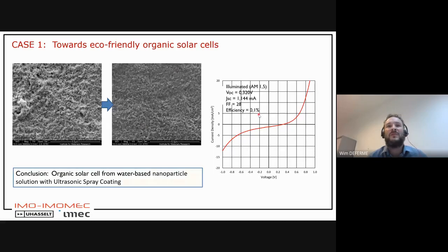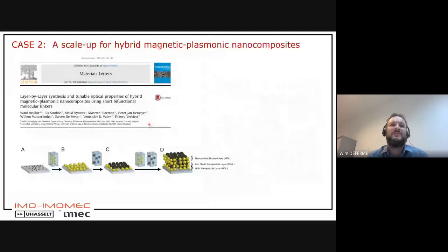And this, of course, has to do with the fact that we heat up our substrate or sample or printed layers or coated layers to 200 degrees centigrade, which is detrimental for these nanoparticles and for these donor acceptor materials that in principle can only take 50 to 60 degrees centigrade temperature treatment. So this is really influencing the efficiency. So this is something we still have to work on to optimize, let's say, the smoothness of the layer and the coverage of the layer to achieve highly efficient devices.